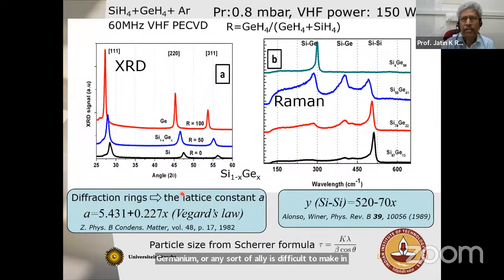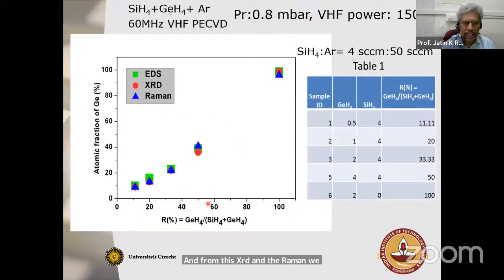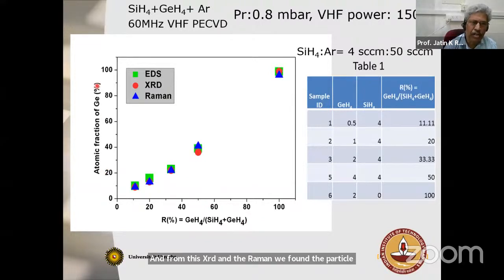But we did that. We used silane, germane, and hydrogen gas with argon, and we started making these particles. From the XRD and the Raman, we found the particle sizes. Not only the particle size, but also the germanium concentration in those particles can be controlled by using a germane to silane ratio in the gas phase. We can make different amounts of germanium go into the system. This has been controlled very nicely, so we can control how much germanium is in the particle.